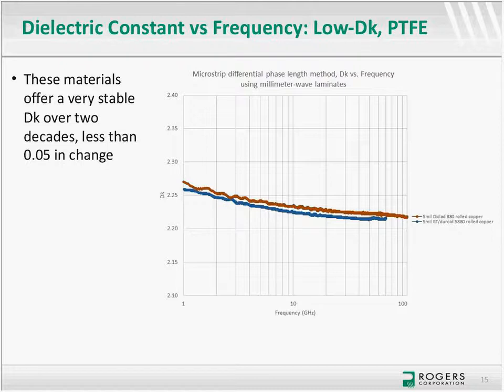In general, in the data that will be presented here, you'll find that the dielectric constant over that broad frequency range does not change very much for these materials. In the case of PTFE, low dielectric constant materials, for this broad 1 to almost 100 gigahertz, you're seeing about a change of 0.05. Unless you're talking about high-speed digital 40 gigabit systems that encompass a very broad band, this overall change probably won't matter so much, because most high-frequency applications in the RF world typically operate in a narrow band of this overall spread that we showed here.